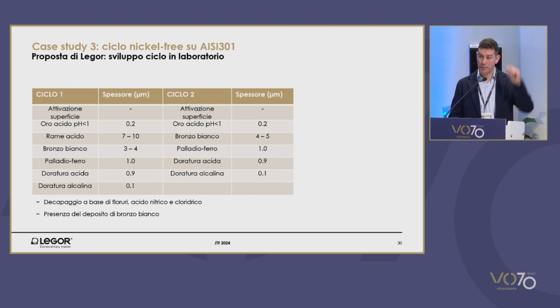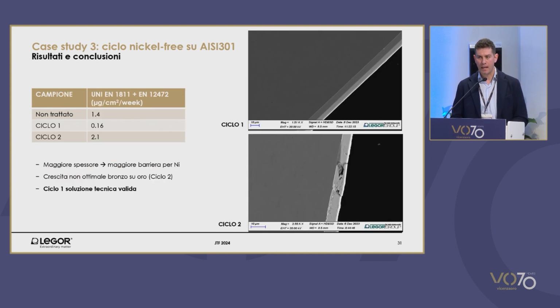White bronze was deposited on the gold layer. It is fully nickel-free. It is a palladium with iron. Acidic gold with 23-karat gold was used, adding an additional substance to obtain the color that was requested. With cycle 1, the release of nickel was below the threshold limit, and cycle 1 actually is a good solution. Cycle 2 yielded releases over the ones that are tolerated.